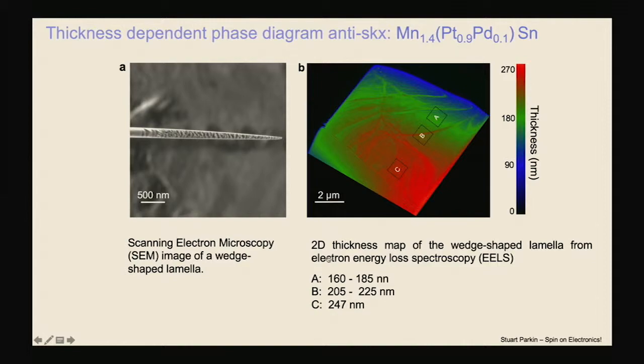What I want to focus on is the dependence of the phase diagram on the thickness of this material, which you might think is not so interesting. Turns out it's quite interesting. So we basically make, using focused ion milling, an 8 micron by 8 micron lamella whose thickness varies across the lamella as shown on the left-hand side, and we measure the thickness locally using electron energy loss spectroscopy intensity.